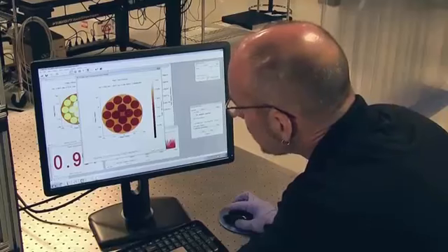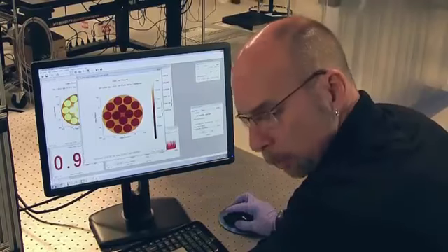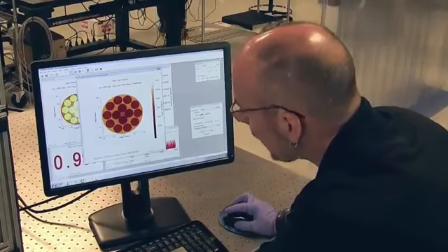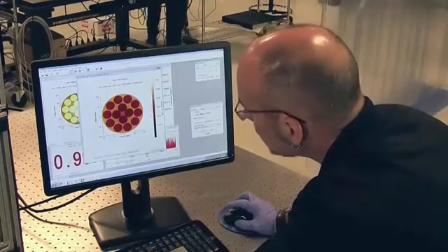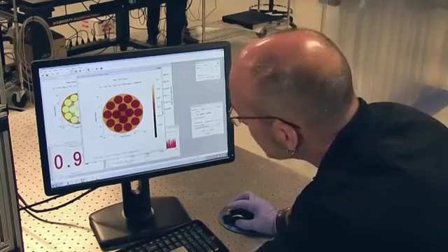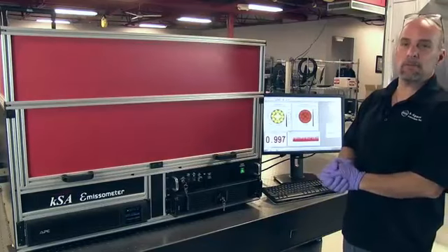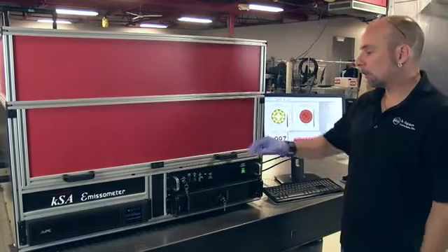What that means is there's going to be a temperature gradient going from pocket to web across this carrier when the carrier is heated up and being used for deposition. And generally speaking, that's not a good thing to have, because that's going to result in temperature non-uniformity across the wafer. Now that the scan is complete, it's a very simple process to unload the carrier.